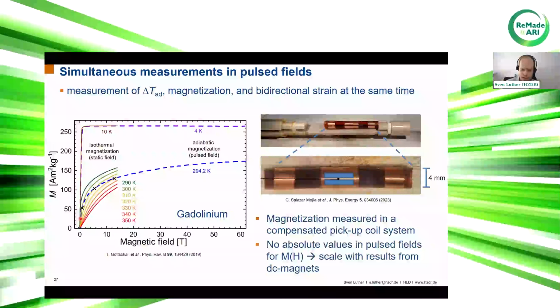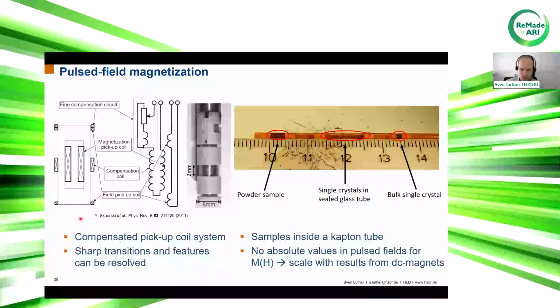But we can not only do these simultaneous measurements, we also put some engineering effort into pulse field magnetization measurements alone. This is a typical sketch of our pulse field magnetization setup, where we only measure the magnetization, with our compensated pickup coil system. Here is again our external field pickup coils. And some effort went into a fine compensation, to have an extremely high resolution of the magnetization in our sample, to really resolve sharp transitions and features by application of magnetic fields.